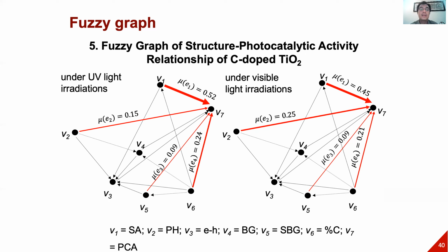Maybe the reason why the electron-hole recombination only contributes around 9% is that the photoluminescence analysis relates to the electron-hole recombination in the bulk of titania. Since the photocatalytic activity occurs on the surface, the electron-hole recombination on the surface needs to be taken into account in the photocatalysis. Unfortunately, the contribution of the surface electron-hole recombination cannot be analyzed by photoluminescence since the contribution is very small relative to the bulk electron-hole recombination.